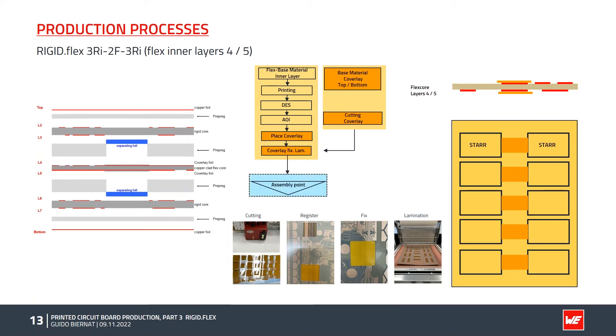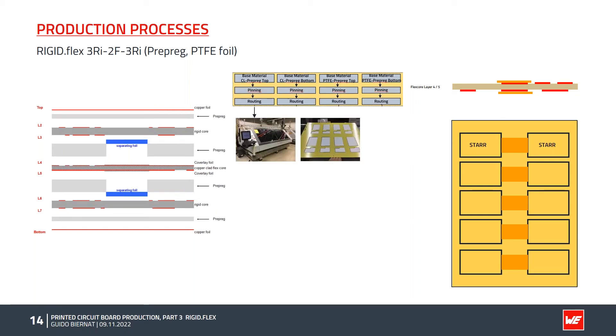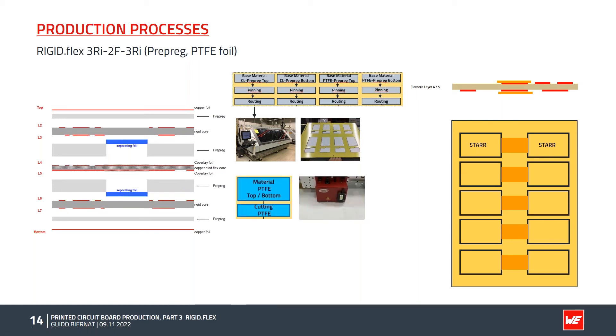The inner layers are then transported to the assembly point in the inner-layer pressing department. This is not standard technology for rigid PCBs — it is only used for rigid-flex. The composite materials required are prepreg, supporting materials, and PTFE foil (a kind of Teflon). These materials go through the typical rigid-flex technology process: the prepreg is partially removed using a routing machine — a window technique — and the PTFE foil is cut with the same cutter machine used for the cover layer.